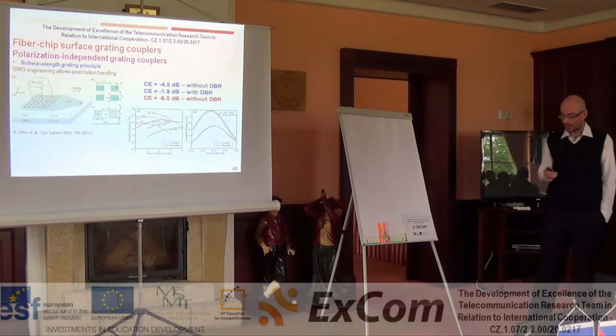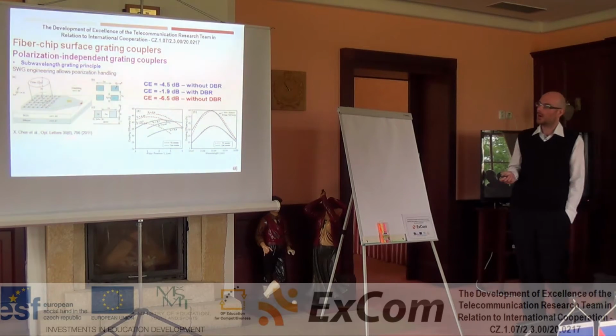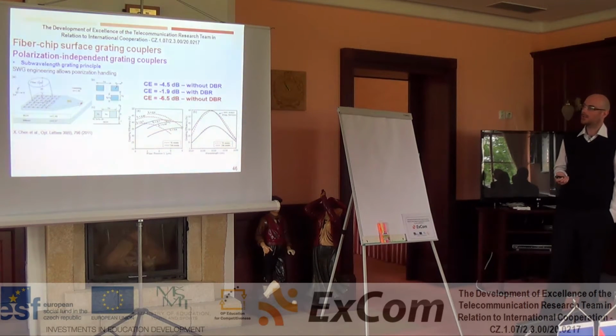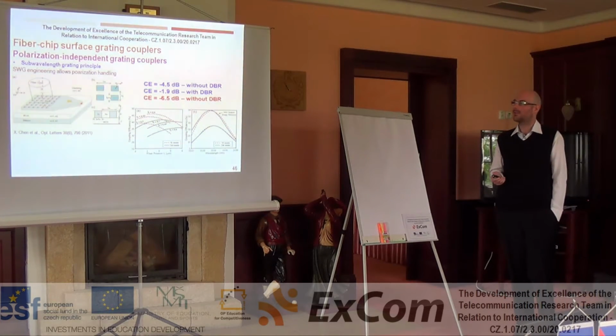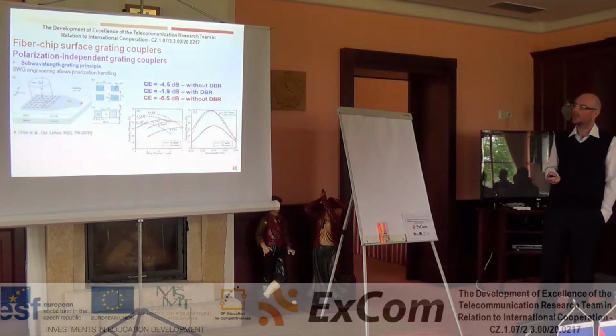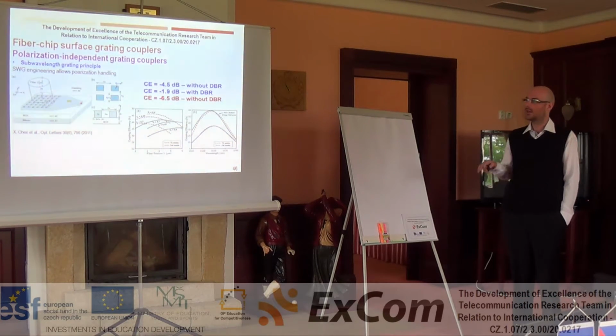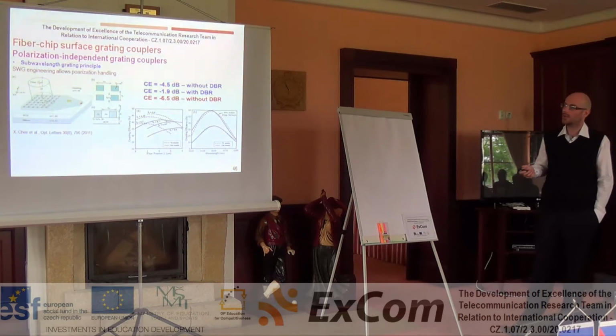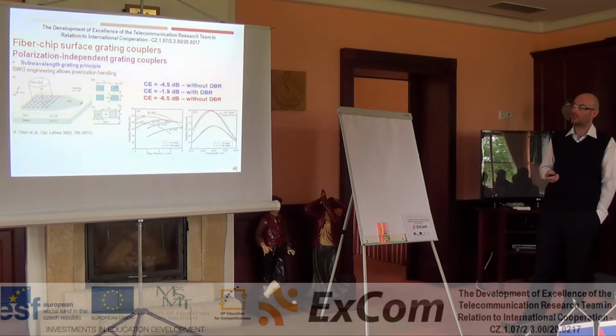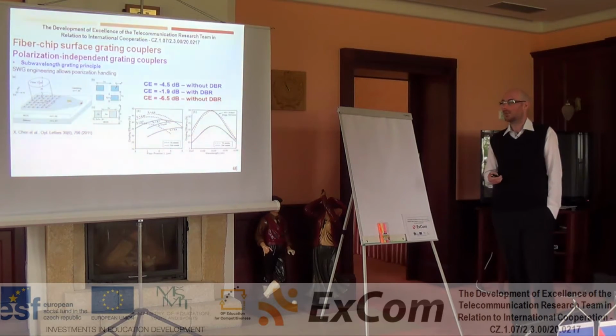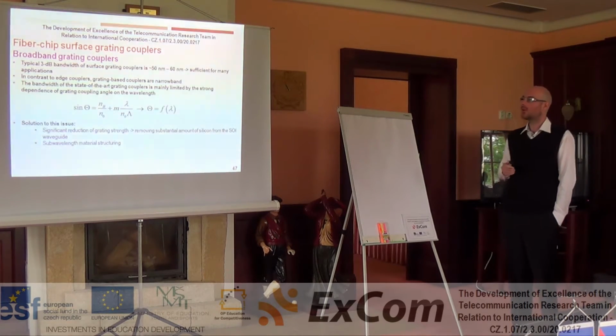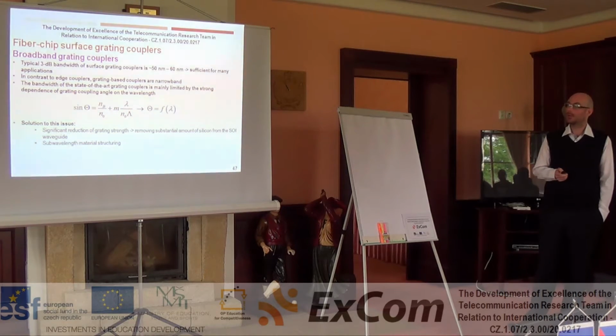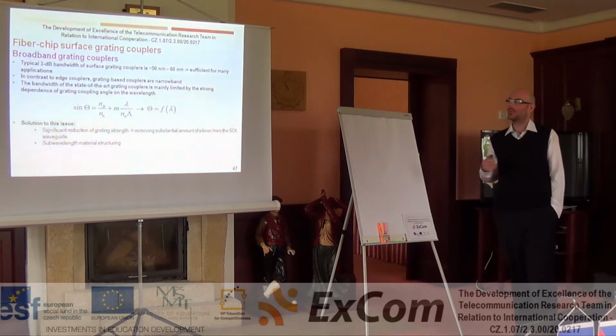This concept has been implemented by a Chinese group, and they achieved experimentally minus 4.5 dB coupling efficiency for both polarizations, and by using a distributed Bragg reflector underneath the grating, they achieved almost minus 1.9 dB coupling efficiency. Okay, the last issue in grating couplers is their broadband operation.